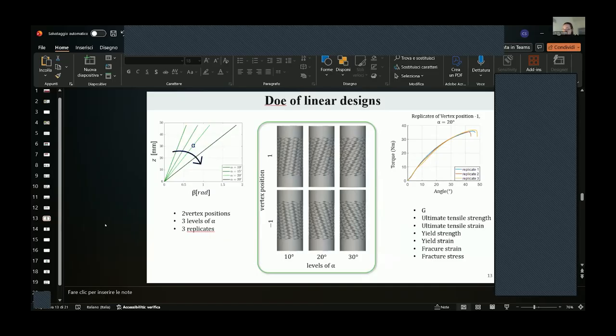The first is focused on the degenerate condition of beta, so beta as a linear function. We have 2 vertex positions, -1 and 1, 3 levels of alpha. We decided 10, 20, and 30 degrees, and 3 replicates per each condition. Then we performed pure torsion quasi-static tests and extrapolated the most important parameters, so torsional stiffness, ultimate tensile strength, ultimate tensile strain, yield strength, yield strain, fracture strain, and fracture stress.